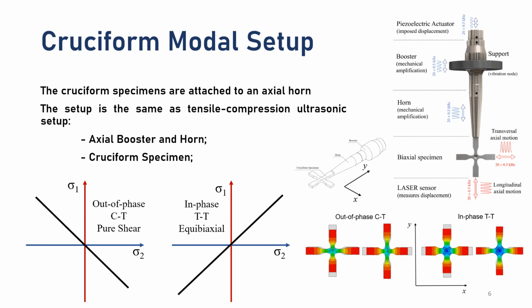So the ultrasonic setup is very similar to tension compression as shown in the first slide. Here we have the piezoelectric transducer, the booster and the horn, which amplify the displacement coming from the transducer, and then the specimen that is excited with the axial displacement provided by the horn. Then we can excite the out of phase and in phase TT and CT to achieve the out of phase pure shear and the in phase equibiaxial.